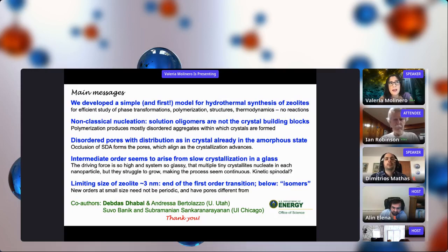I think this is a great question. There are very few cases in which people have done what they call true amorphous zeolites, because everything at this scale looks amorphous in X-ray, but they're not, and they use IR to detect that. And they also find catalytic activity. Nevertheless, the catalytic activity of the real crystalline zeolites is slightly better. So the size of the pores and the catalytic activity are important in the amorphous zeolites, but the pores have higher selectivity in the case of the crystal.